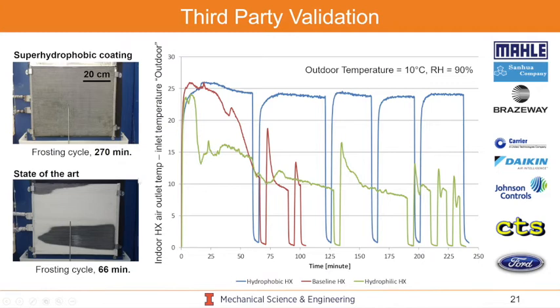We've been able to show very efficient performance where you can imagine these curves, the higher they are, the better it is for your overall efficiency. So you could think of this as a temperature difference from indoor to outdoor when you're using that heating mode. And you want that temperature difference to be high because you want to maintain your home to be warm in the wintertime. But you could see that because of frosting, these uncoated heat exchangers will accumulate frost and they'll decay in performance over time. So we're very happy with these results. And this is a very good proof of concept of the fact that tailoring these interfaces in a very scalable way can really affect your energy savings on your real life systems.